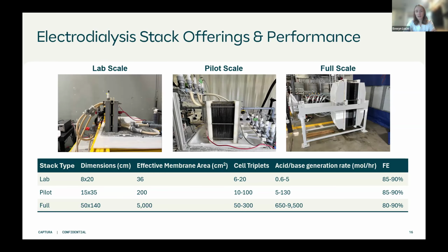And the design of that channel is really critical for improved efficiency within the full stack. So if you were to take all commercially available membranes and put them inside the stack, we would actually have improved efficiency over a commercial stack already without the replacement of our membranes, which is really exciting progress for us. So the first stack that we developed was a lab scale stack. That's the first image you see here, 8 by 20 centimeters. And typically we test these with 6 triplets. We have, I believe, 5 of these now on site. So we're able to iterate a lot at this scale, as well as run stability measurements at this scale for the full stack stability.